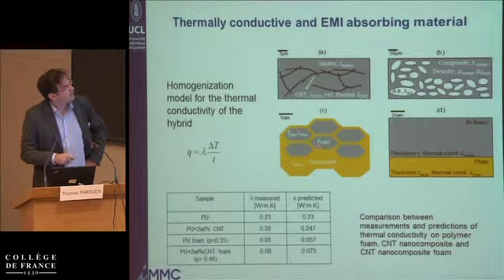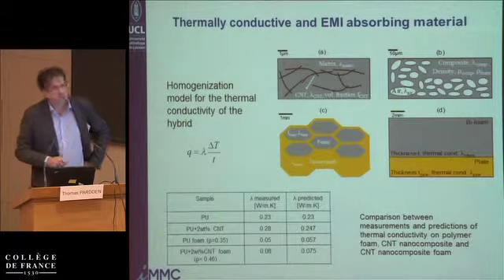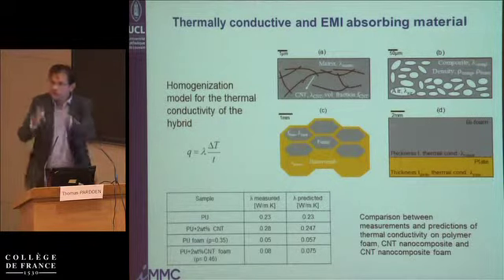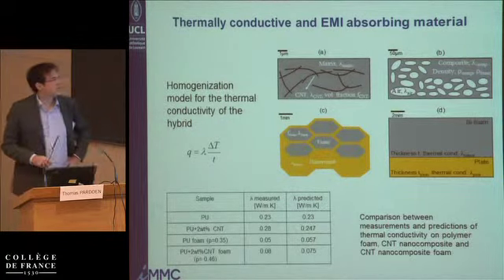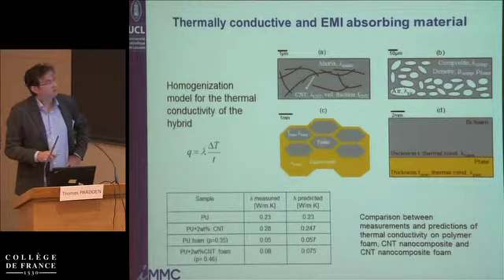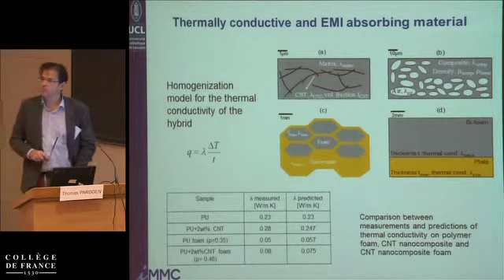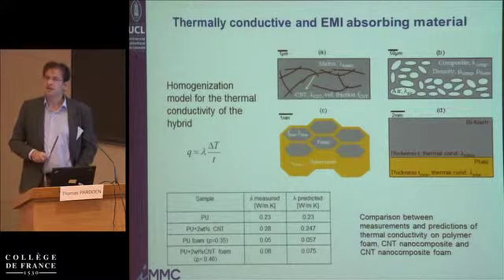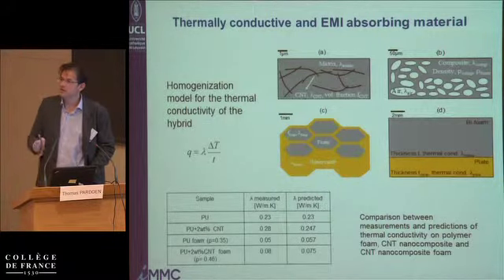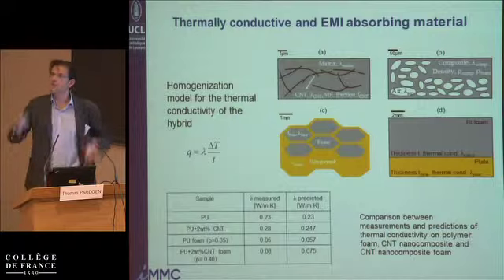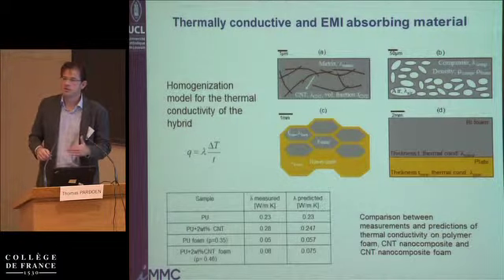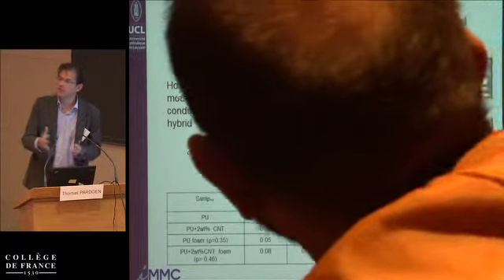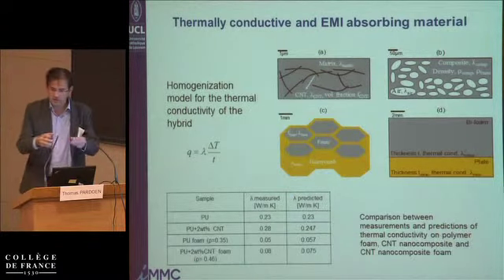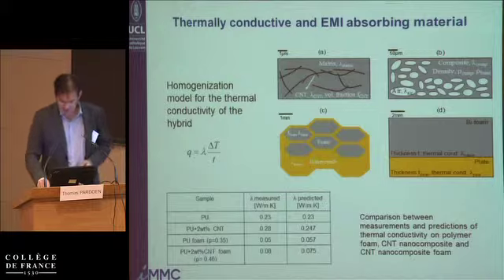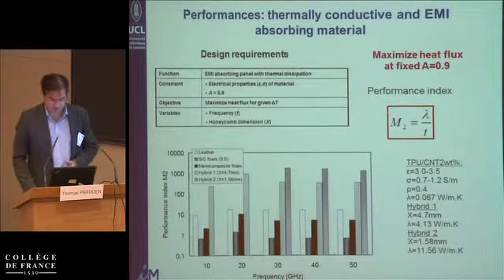The only heat that is transported really is through the face of the aluminum honeycomb. But of course, you could play around and even improve the insulation by replacing the aluminum honeycomb by a Nomex honeycomb and metallize the surface of the Nomex, which would give the insulation of the Nomex material, or polymer-based honeycomb, and still have this waveguide effect by metallizing the surface.